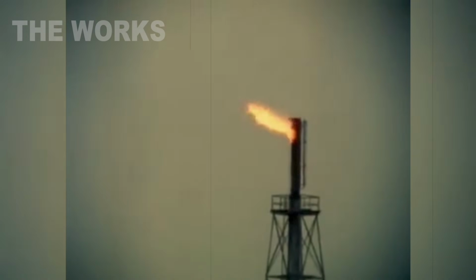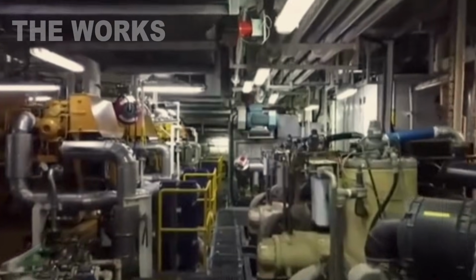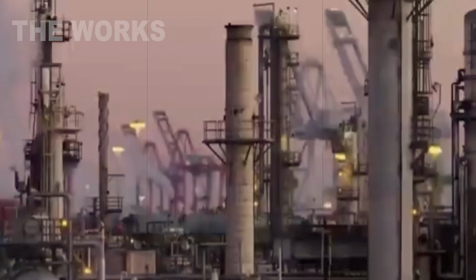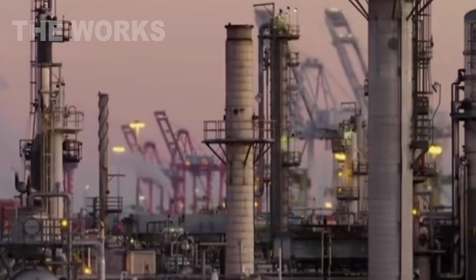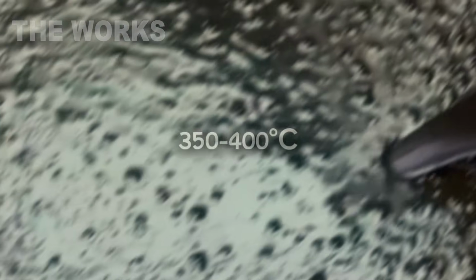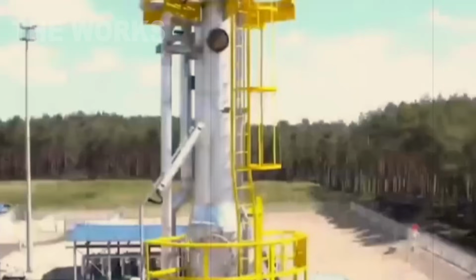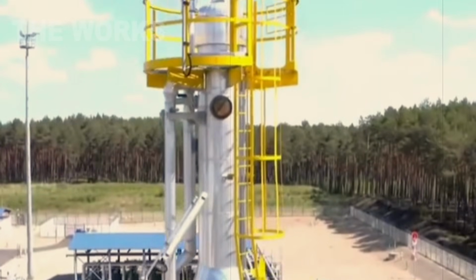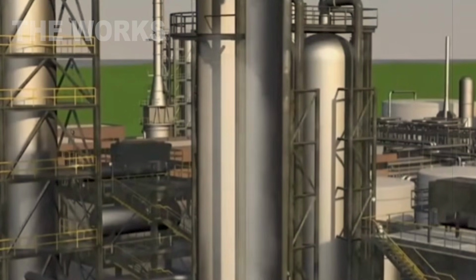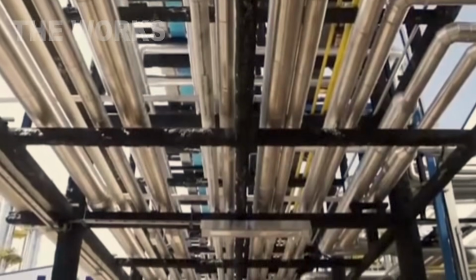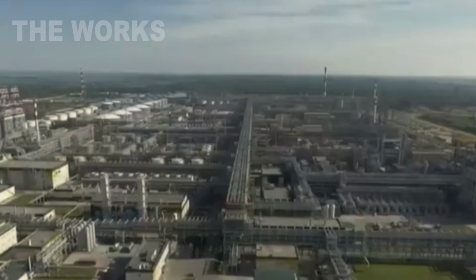Crude oil itself is a complex cocktail of hundreds of different hydrocarbons. To turn it into petrol, it must undergo a series of technically demanding stages at a refinery. It all starts with fractional distillation. The crude oil is heated to between 350 and 400 degrees Celsius and fed into a tall distillation column. The various components of the oil vaporize and rise to different heights inside the column before they cool, condense, and are drawn off. The petrol fraction is one of the lightest, and it's typically collected at a temperature between 40 and 200 degrees, but this initial distillation only yields about 15 to 20% petrol.